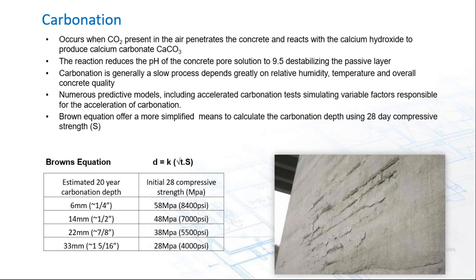The reaction reduces the pH of the concrete pore solution, destabilizing that passivating layer. Carbonation is generally a very slow process and depends greatly on relative humidity, temperature, and overall concrete quality. There are plenty of predictive models out there, including accelerated carbonation tests simulating variable factors responsible for acceleration of carbonation. But the one that really puts it in fairly simple terms for me is Brown's equation, that says